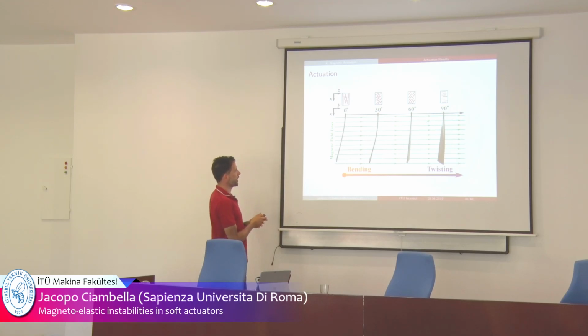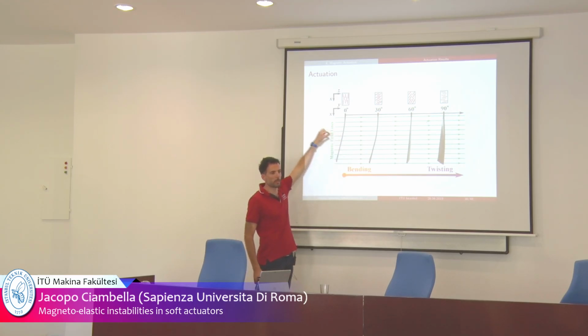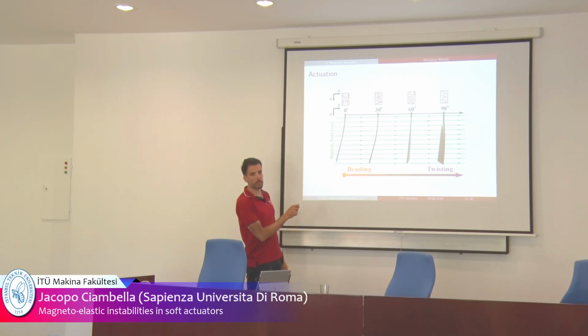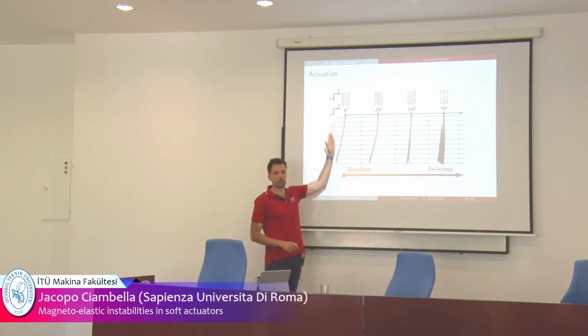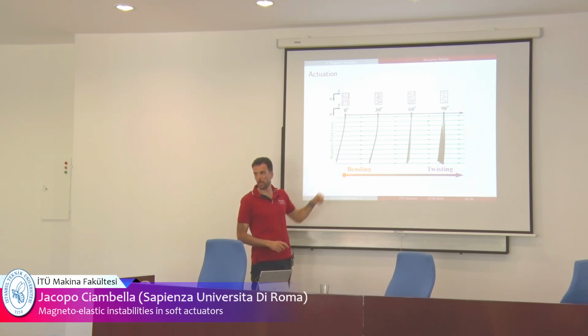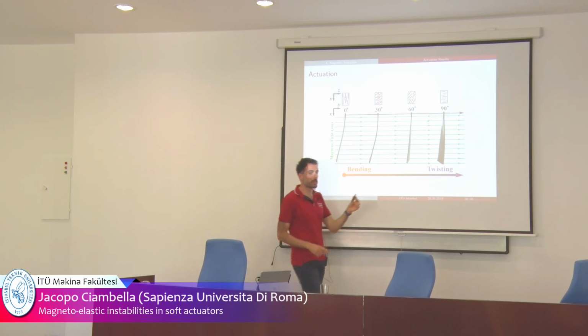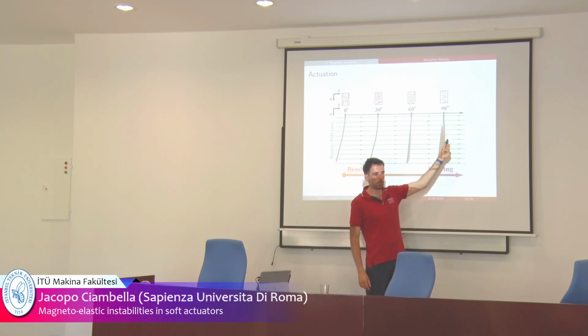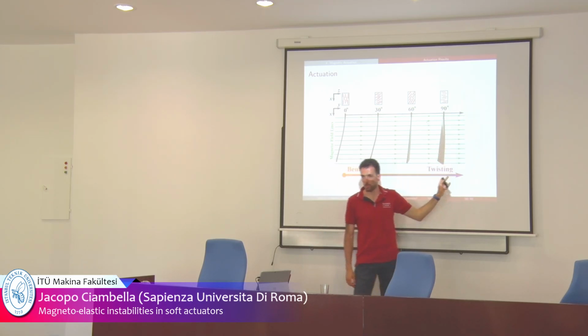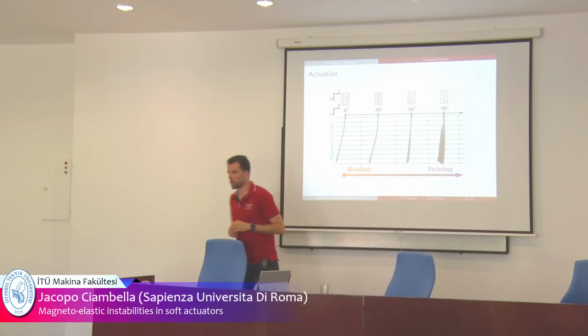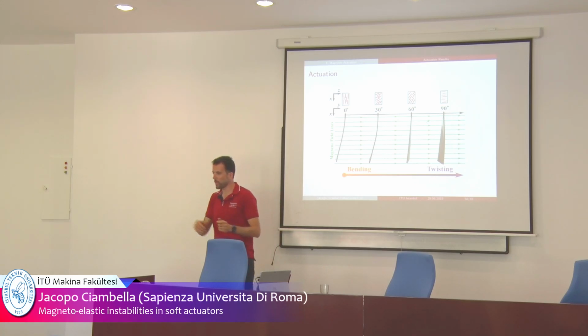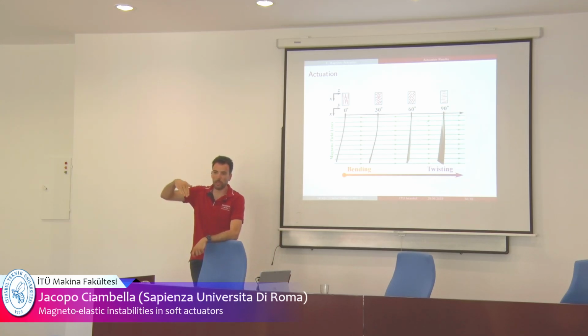And this is what is happening here. This is a real specimen in a cantilever configuration. So this point is fixed, suspended within these field lines here. So if the fibers are 0 degree, means that they are oriented in this direction, you obtain bending. If the fibers are 90 degree, in this case 90 degree means outside the plane of projection, you will obtain twisting. Okay? And so by modulating the orientation of the fiber, you can pass from bending to twisting. And this would be very nice. So you can have a flap that can either bend or twist. Okay?